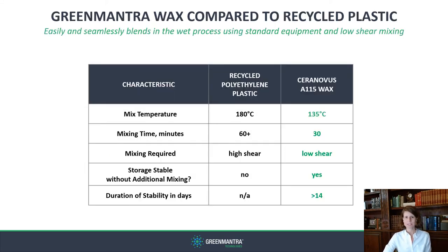Green Mantra waxes offer a revolutionary way to add waste plastics to asphalt while simultaneously enhancing performance. Compared to standard recycled plastics, Green Mantra waxes are easily mixed at lower temperatures with standard low-shear mixing. They remain stable and fully incorporated in the liquid asphalt binder for a minimum of 14 days with no additional mixing required. The ease of use and long-term stability of Green Mantra waxes translates to differentiated performance in asphalt compared to standard recycled plastics.